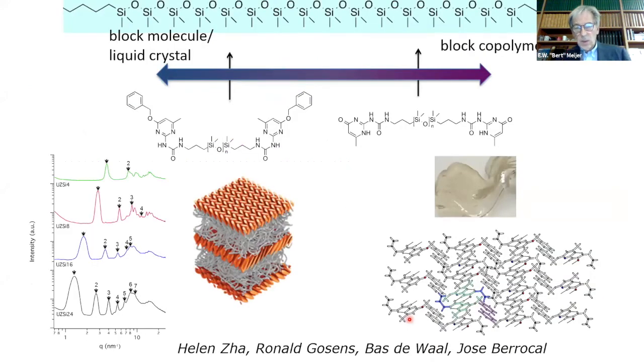So now we have them, the siloxanes, and we try to use them as a discrete material-like, solvent-like fragment. And it gives a lot of interesting possibilities, we think, because the molecules we make are somewhere in between a block copolymer, or a block molecule, and a liquid crystal. I'd like to show you an example. This is a supramolecular polymer with siloxanes of different length. They act like a block copolymer. This part doesn't like to be dissolved in this part, and then the ratio between the two determines whether it's a lamellar or a cylinder or whatever.